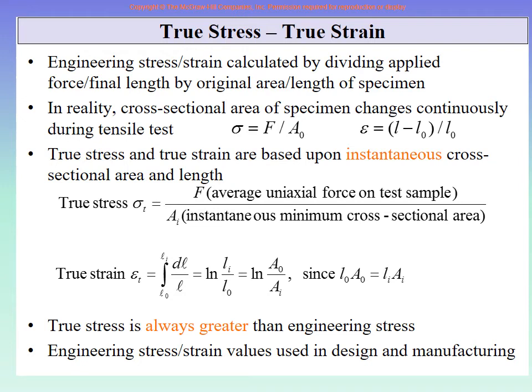But right, so this is the true stress. The force is the same as in the engineering one, but the area is the instantaneous or the current area rather than the original area. Now, if you keep on changing the length, then this is the integral definition, dL upon L. If you remove the integral, it is delta L upon Li. The good thing is that if you know your integration, 1 upon L dL, then it is ln of that, right? So it is very simple.